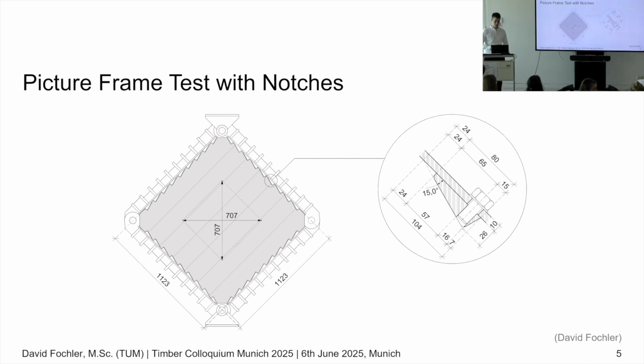The result is, first of all, one disadvantage, because the test specimen gets a lot more complex in its form with all its edges and corners. So those small notches we have to create in the test specimen are not easy. But we hope for one huge advantage compared to all other available methods, and that's that the notches should allow tests with all kinds of elements. Not only with diagonal layers, but also with mechanically jointed elements, as well as the usual glued CLT. So we should be able to test everything in this frame.